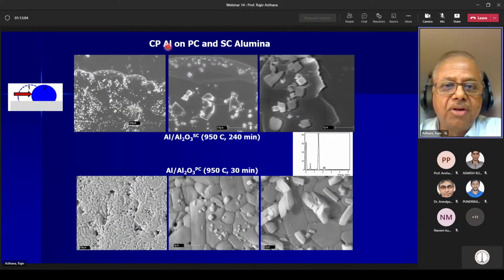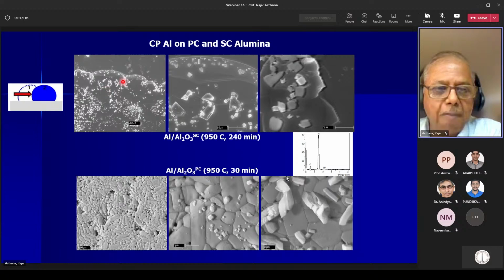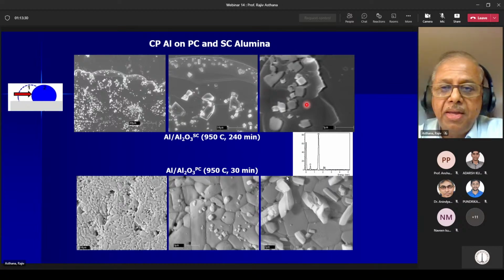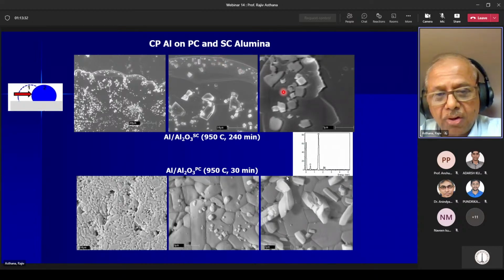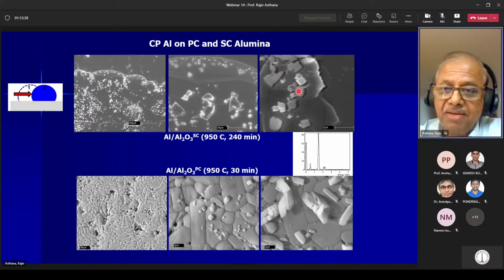These are some results on liquid aluminum droplets on aluminum oxide, polycrystalline and single crystal. These are single crystal. So we push the droplet and now you're looking from the top. This is the area where the droplet was sitting earlier. And you actually see some aluminum oxide crystals forming under the droplet after the droplet was pushed away. Obviously, alumina is a so-called non-reactive system, but because you have dissolution and reprecipitation taking place, these little aluminum oxide crystals form. We see the same behavior with polycrystalline aluminum oxide substrate.